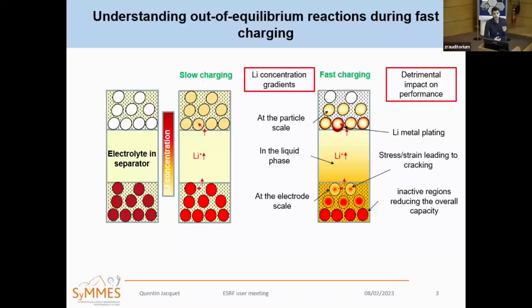you're basically going to try to pull off lithium from your material faster than it can diffuse in it at the different length scales. That's going to create concentration gradients at particle, in the liquid and at the electrode scale. And this is detrimental for the performance of your battery.